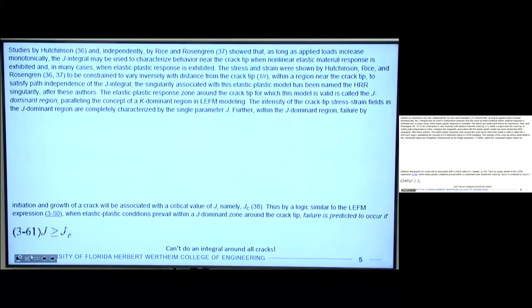Okay, so this is a slide with a lot of words that I said a lot of them already up front. And so really what they showed is that when the J integral for any arbitrary path around a crack supersedes the J integral that is critical, or a critical strain energy release rate, then we would predict that this crack would propagate. And so this is what they did for cracks, when I just remind you, these are that have elastic plastic conditions, when those conditions prevail. So when it's not a K-dominant regime, but a J-dominant regime where there's a lot of plastic deformation. Okay, so that is helpful sort of in a fundamental sense. If you are the fundamental type, you can go play around with this and calculate things.